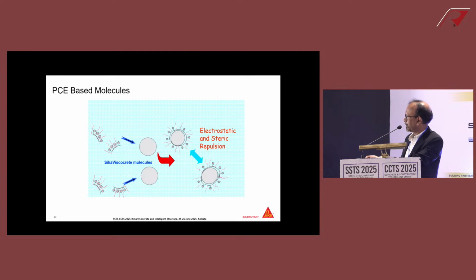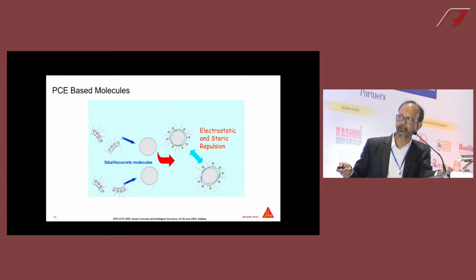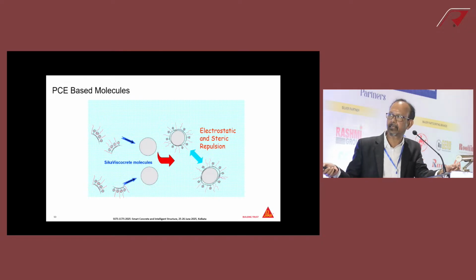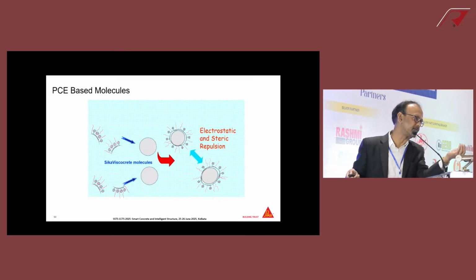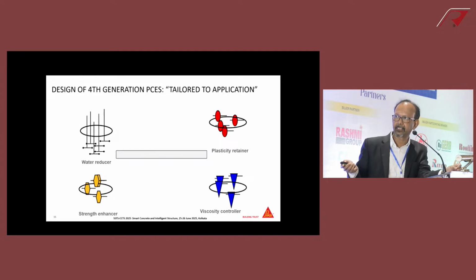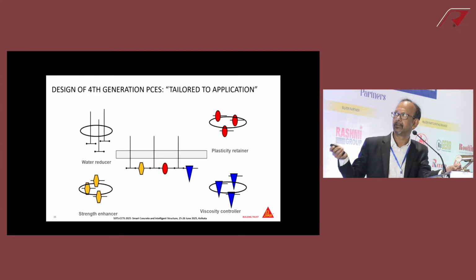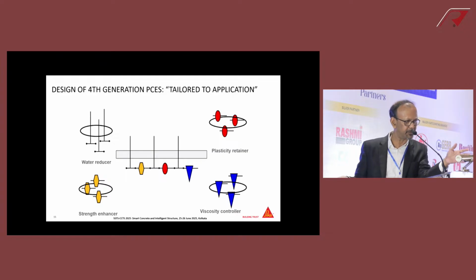So if you see, these are the molecules. This is the cement particle, and basically coating around the cement particles, like charges repel each other, and that's where the available water, which was held in the form of flocks, is released. This is just to give you an idea, because when you tailor, you take into account the water reduction capability, the strength enhancing capability, the viscosity, which is the ease at which you can mix, and the plasticity retention.